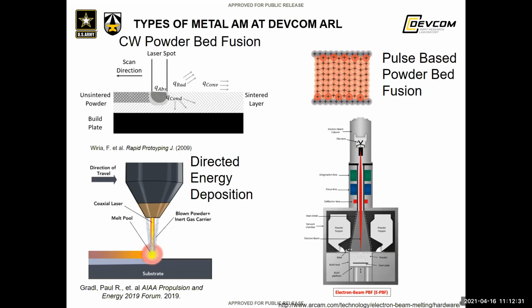We also are moving into larger scale manufacturing with directed energy deposition. That is where you're able to build layers on top of itself without a powder bed, and the powder is blown into the laser itself. This usually has a much larger width, and you use a larger powder particle size, and you can create larger objects. This is really good because you can have several parts on the same build plate that don't have to be built at the same time, as well as you're able to use this for repairs easily in the field.